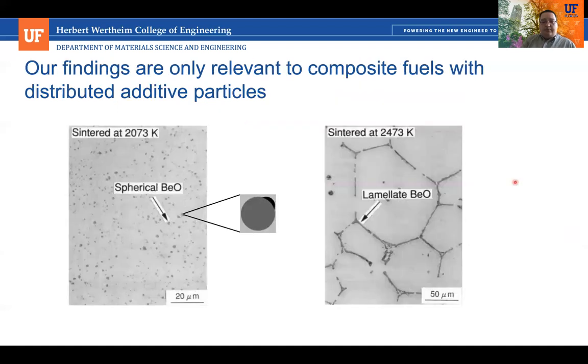So we've now demonstrated that the bubbles can have a large impact on the thermal conductivity of these additives. And we've also developed a model that can start to capture that effect. But these are very simple simulations, and they are really only applicable to dispersed microstructures. For microstructures that are continuous, the bubble interactions are going to be different, and they're going to be more spread out across the grain boundaries.